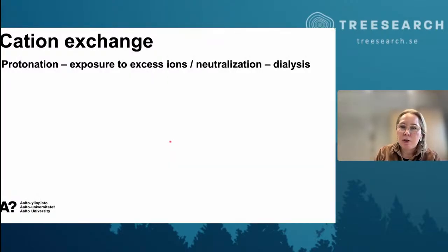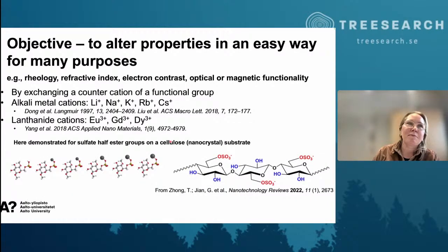So the cation exchange is done with salts of the cations in an aqueous system, where we protonate first. An important detail to notice is that all of the work in this presentation is now using these sulfate half ester containing cellulose substrates.